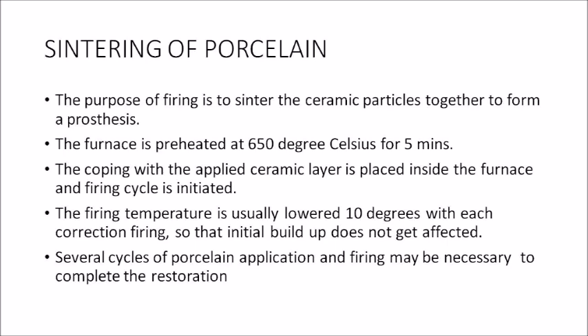The firing itself is a cycle. We'll have to do the firing cycle after each layer of ceramic applied. The firing temperature is lowered by 10 degrees with each layer of ceramic, that is each correction firing, so that the initial buildup does not get affected. Several cycles of porcelain application and firing may be necessary to complete the restoration. First we'll do the application and firing of the opaque layer, then the dentinal layer, then the enamel layer, followed by glaze. Each layer can be done in multiple stages.